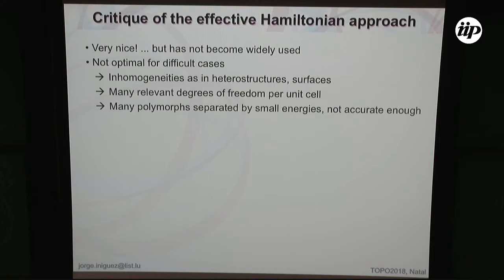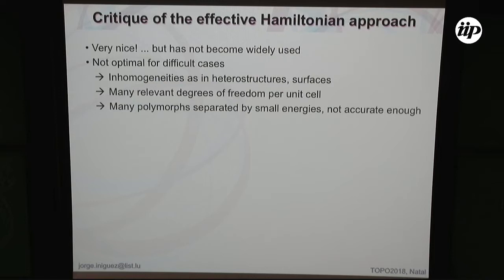This approach was applied very successfully to, for instance, lead zirconate titanate, to understand its phase diagram and why this material is such a good piezoelectric. Many things have been done very successfully. But over the years we have also found that when you go to more and more complex cases, things become more and more complicated. You really need to know a lot about the material before producing a model — which local degrees of freedom are important, which interactions, which ground states. And if you go to a superlattice, it becomes even more complicated.